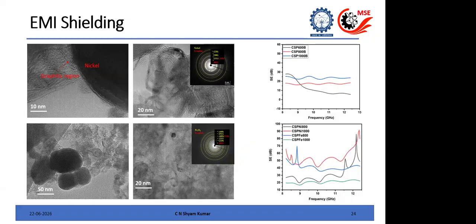And here the trend is reversed. If you increase the graphitization temperature from 600 to 1000, you have an improvement in the EMI shielding, because now it is becoming more conducting, and here you need more conductivity, and the porosity is increasing. So you will have local internal reflections and all, which improve the EMI shielding. And if you increase it further with catalyst, you increase the EMI shielding.